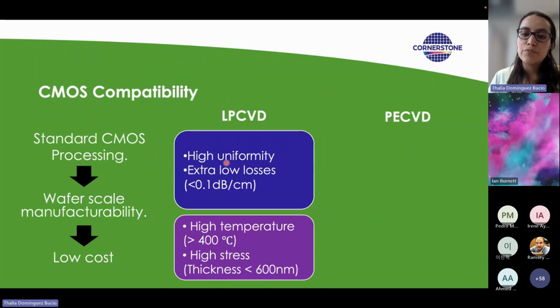Now, the disadvantage of this process is that it's done at a very high temperature. Why would this be a problem? The problem is that if, for any reason, you want to integrate your silicon nitride with other materials, such as silicon, and you have an active device that has doping, if you heat it up at high temperatures, you will detrimentally affect the performance of your active devices.